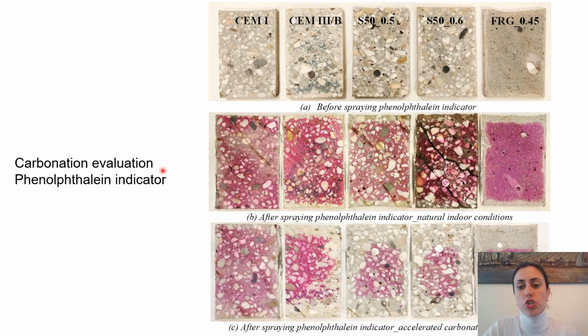When it comes to carbonation evaluation, as you can see, there were here five samples. I also added one on a fiber reinforced geopolymer concrete. This was before spraying with phenolphthalein, and the second and third rows are after spraying the phenolphthalein. The phenolphthalein indicator is not the best indicator for the carbonation front in alkali activated materials. You can see here the front is very close to the border, while after spraying the phenolphthalein, that border moves much lower.